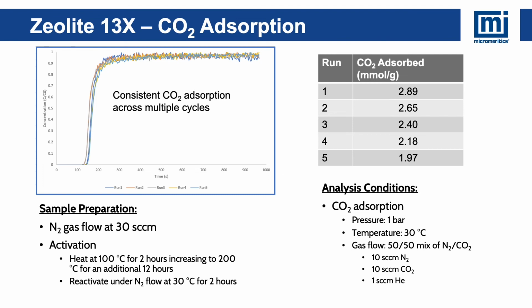First up, let's look at zeolite 13X for CO2 adsorption. We see fairly consistent CO2 adsorption across multiple cycles. We do see a slight drop off in capacity as we go from run 1 to run 5, likely as a result of not being able to fully reactivate this material without additional heat, as we are keeping our reactivation consistent at 30 degrees C for all these samples.